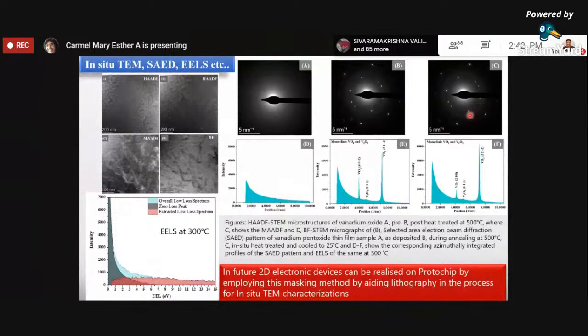This means vacuum heat treatment of the amorphous vanadium oxide layer directly influenced the formation of monoclinic VO2. Later we understood that formation of monoclinic VO2 is a very tough task, because in phase transition theory monoclinic VO2 is majorly considered, and synthesis of pure monoclinic VO2 is also a challenging task. That also we have demonstrated with this work. This is one typical example of electron energy loss spectroscopy, taken at 300 degrees centigrade. This work is yet to be published.